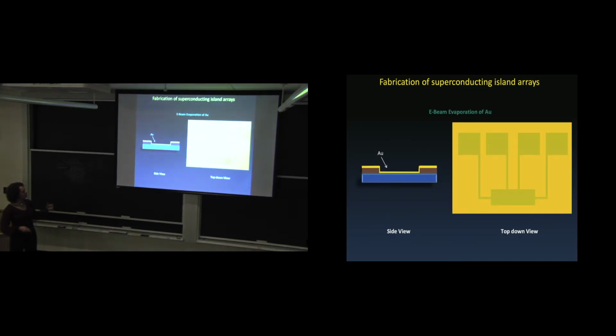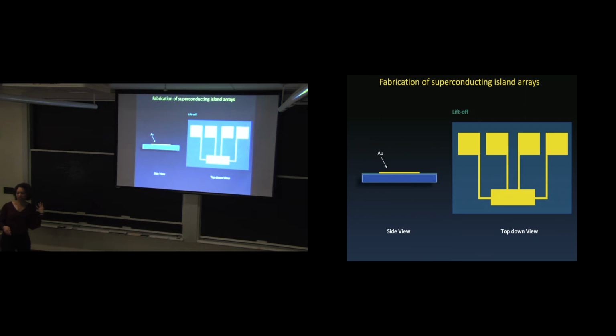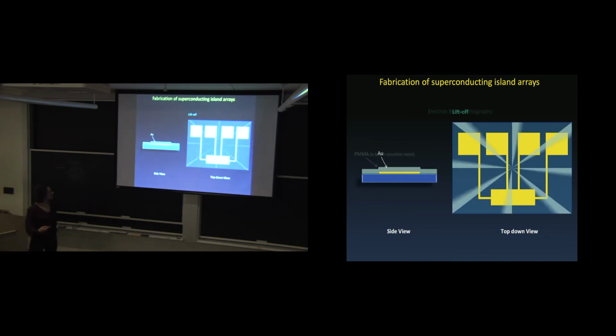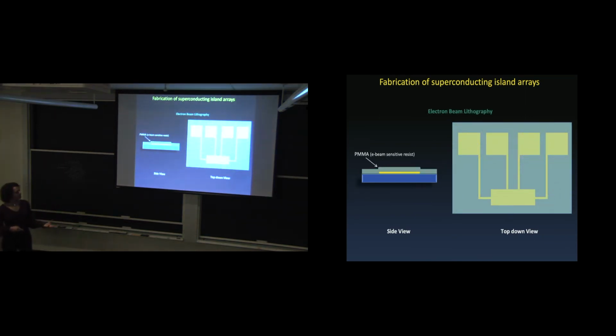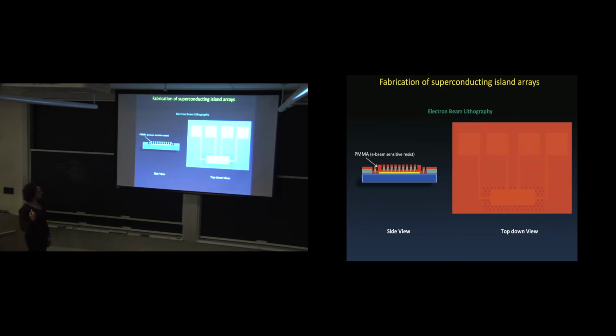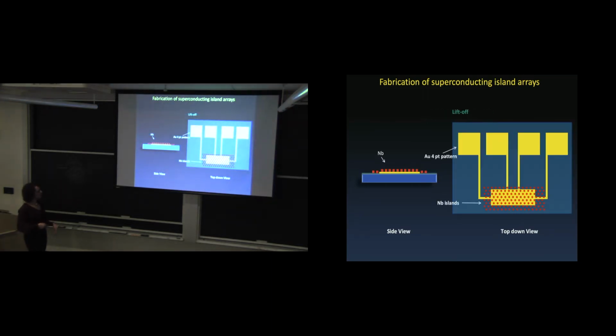In this case, we then deposit gold. And then the photosensitive material lifts off in acetone. We put the whole thing in acetone, and it breaks off here, and breaks off here, and leaves just our pattern behind. Okay? And then we do the same thing with the holes. We put on an electron beam sensitive material, and then use magnets in the electron beam lithography system to drive the beam around with a shutter and expose just where we want it. So we make all these holes across our system, and then we develop that, deposit niobium, and then lift off again, and we're left with our 4-point measurement pattern covered with holes.